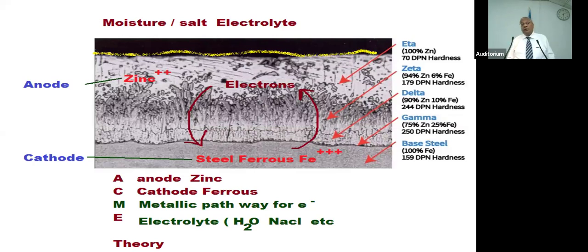I agree. But what about the 20 microns of pre-galvanizing? No, that is not enough. That is why when you use C purlins in marine drive houses, they are corroding, because the thickness is not enough. So what we say is you have to understand what you are going to purchase from the market. Are you getting a hot dip galvanized 80 micron product or a pre-galvanized 15 or 20 micron zinc layer? So now this is 80 microns.